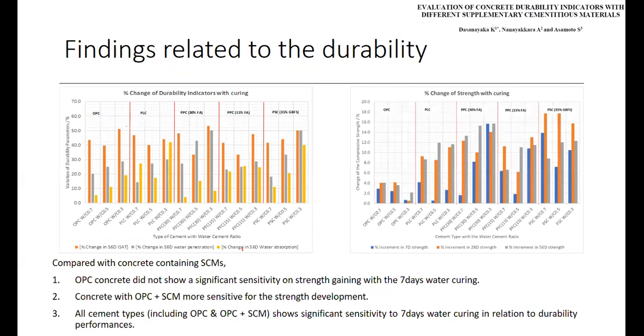This is also one piece of research we have completed and published already. You can see the improvements. Here we have utilized different combinations: OPC, OPC plus 15% limestone, OPC plus 30% fly ash, OPC plus 15% fly ash, and OPC plus 35% ground granulated blast furnace slag, and identified them with different durability indicators. We utilized 56-day initial surface absorption, 56-day water penetration, and 56-day water absorption.